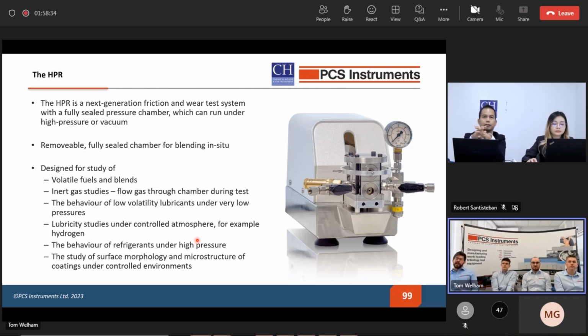We can look at the behavior of these lubricants under very low pressures, almost vacuum. We can do lubricity studies under really controlled atmospheric conditions. What's quite popular these days is hydrogen, for example. So we could test the behavior of tribological contacts under hydrogen atmosphere. We can look at refrigerants under high pressure. So the HPR offers a wide variety and versatility of different environments that tribology contacts can now be tested under. And this can be ordered as well from PCS.